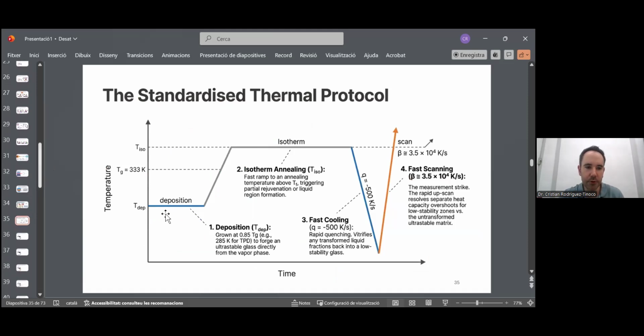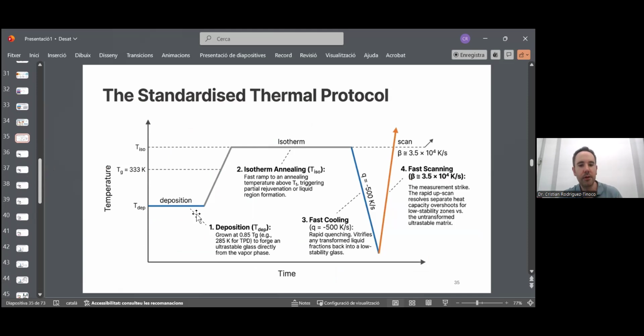Now we study this process. We have our glass that we deposit at a given temperature. If we want the ultrastable state, we grow it at 85% of the glass temperature. Then we go above TG, to a temperature at which we want to study the transformation process. It has to be above TG, of course. And we do an isotherm at this temperature, and we choose a time, say 1 hour at this temperature. And then we cool the system down to the glassy state.